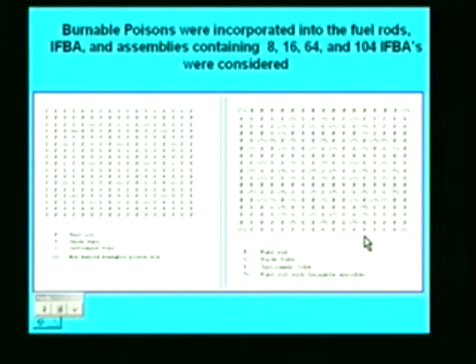And what we've done here is incorporated burnable poisons into the fuel rods. This is not unusual. They're called IFBA, Integrated Fuel Burnable Absorber rods. We've looked at assemblies containing 8, 16, 64, and even 104 rods. And this is a case where we have a PWR fuel assembly with 64 burnable poison rods.